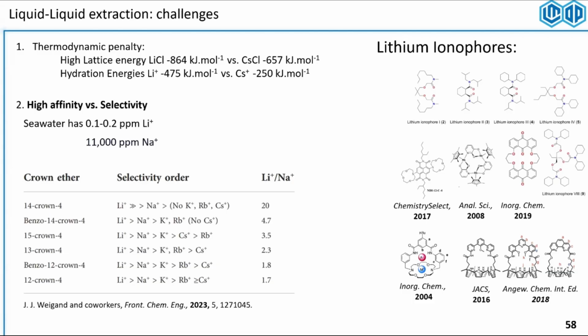And the best lithium ionophores that are reported to date have nearly 20 specificity to lithium versus sodium, meaning that if you have tens of thousands of ppm of sodium and magnesium and strontium and calcium inside the sea salt or seawater, the brine, it might not even touch lithium at that low concentration of 0.1 ppm or so.